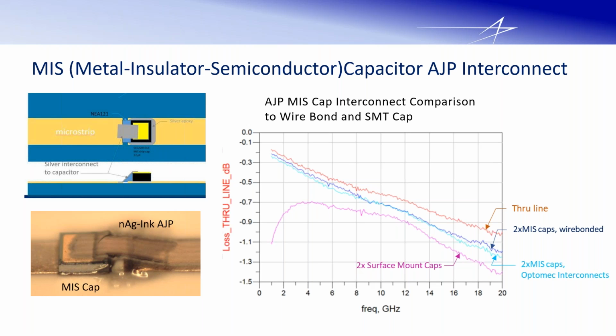So when you're doing high frequency, we have these MIS caps, these planar caps, and typically they have a wire bond to them. So they're soldered down, have a wire bond, but the wire bond has a larger footprint. It's got some parasitic inductance losses. So we said, well, if we can print that connection and get rid of these problems, that would be something that we could add, because we use these MIS capacitors all over the place in our RF designs. So this was our first trial at it, and we're pretty pleased.